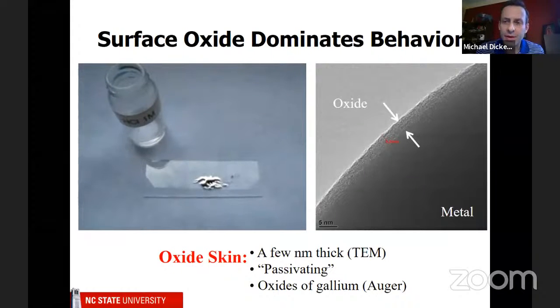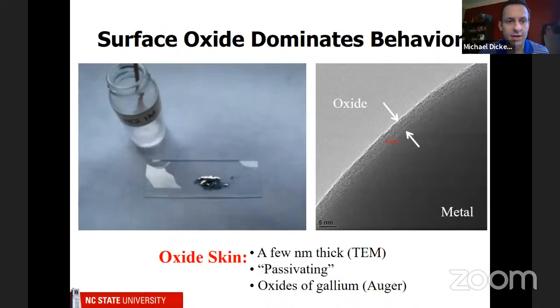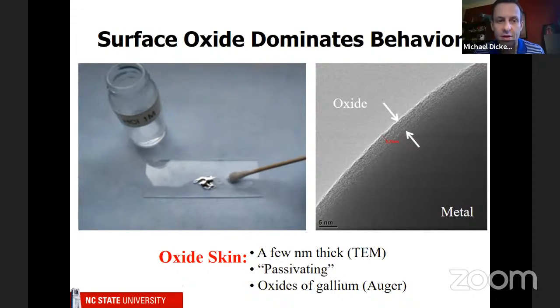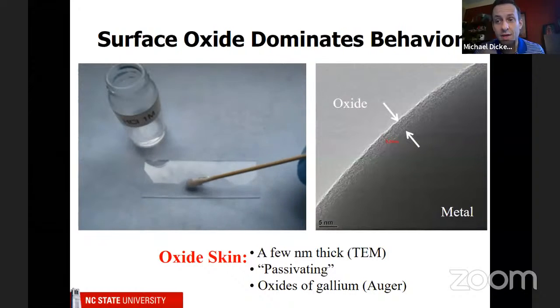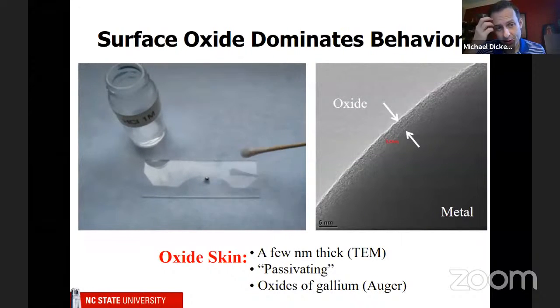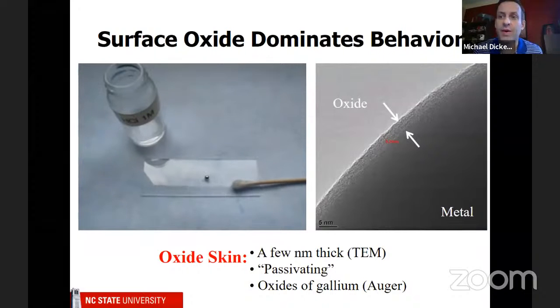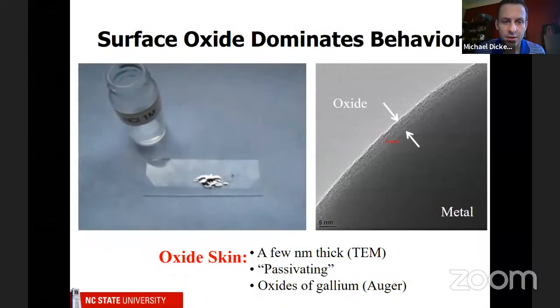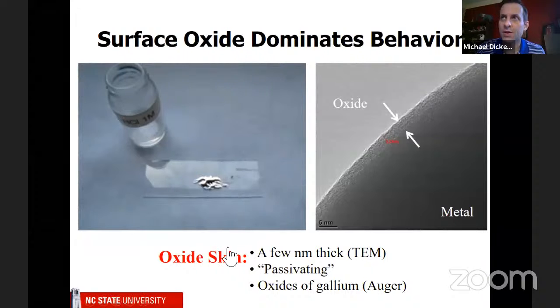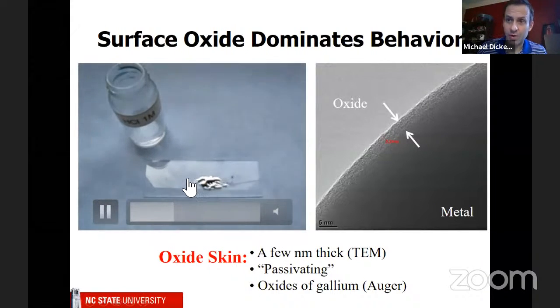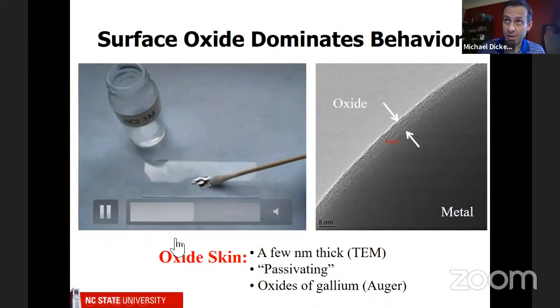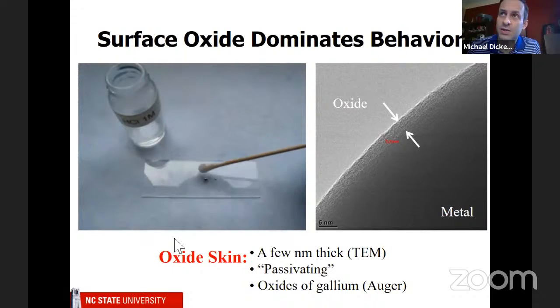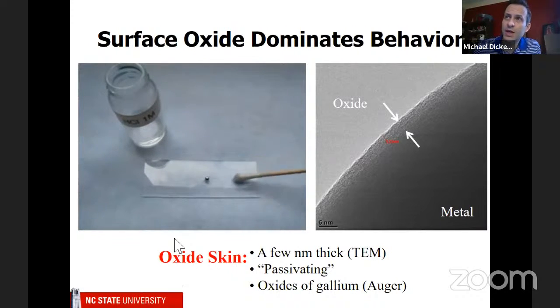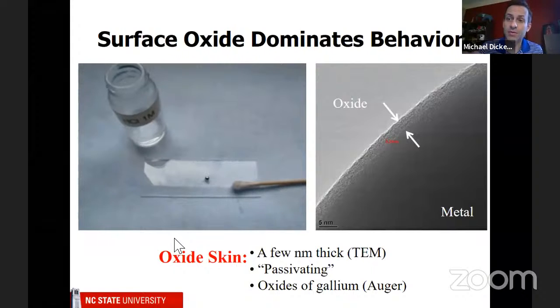As a reminder, one of the key ideas that I presented on Monday is that these liquid metals react with air and form a very thin oxide layer. And that oxide layer allows the metal to take on shapes that would not normally be possible with liquids. So I'm going to play this one more time so you can see that initially the metal is spread on the glass slide, sort of like paint. But then if you take this Q-tip, which has a little bit of acid on it, that acid removes the oxide layer and the metal will bead up.